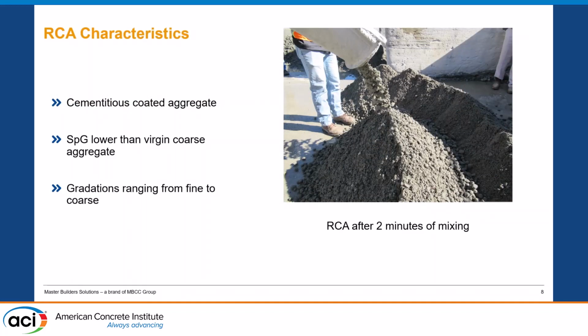So one of the main things, of course, as we just saw in the previous presentation, we need to characterize the material, and that is essential. What we're talking about here is basically an aggregate that is coated with a thin layer of combination of hydrated and unhydrated cementitious materials. The density is slightly lower than the virgin coarse aggregate would be, considering that it has also a little bit of sand, water, and of course the cementitious material. In the example that I will give next, the virgin limestone, for example, had a specific gravity of 2.8, and the reclaimed material that we made using that aggregate ended up with a specific gravity just over 2.6.